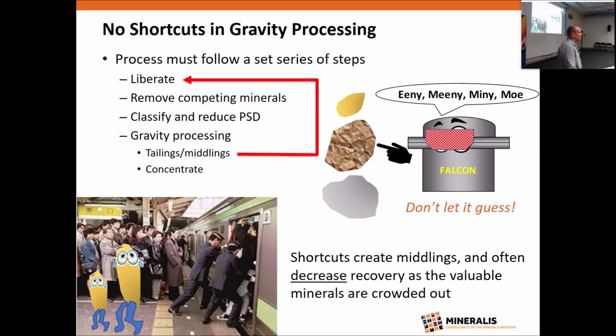But it's quite common to observe that steps in gravity processes will be missed, or the consequences of actions taken are not well understood. An example we see very commonly is people will open the aperture on a screen before a Knelson or a Falcon in a gold plant, and they're trying to get more feed into it to increase the recovery. And that might actually have the opposite effect, because what they're doing is letting in lots of particles with a similar apparent SG, and they crowd out the valuables.